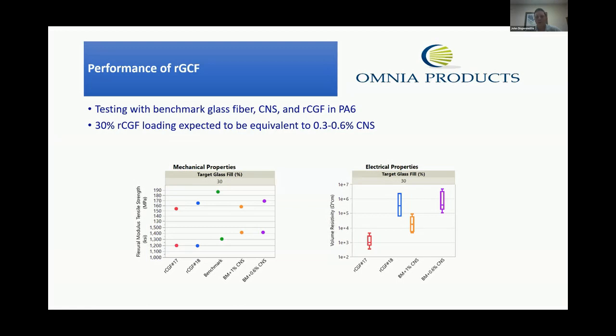So the amount of CNS that is still left on the glass was expected to be something in the range of 0.3 to 0.6% of CNS still left on the glass. So looking at the data, it does coincide very similarly to what a virgin product with CNS resulted in. So the project has been very successful from that standpoint of view in developing a product and process from the reclaimed material.